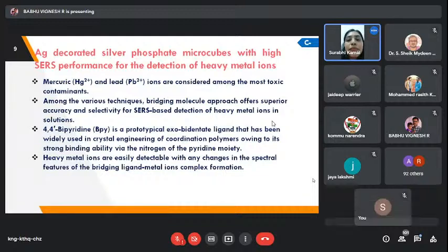So among the various techniques, the bridging molecule approach offers superior accuracy and selectivity in SERS-based detection of heavy metal ions in solution. In this paper, I have used 4,4'-bipyridine as the prototypical exobidentate ligand, widely used in crystal engineering for coordination polymers owing to its strong binding ability via the nitrogen, as you all know. Heavy metal binds together with the silver phosphate, as well as the heavy metals. So there is a bridge-like mechanism that takes place because of the charge transfer mechanisms, and hence it is very useful for detection of both the heavy metals at very low molecular levels.